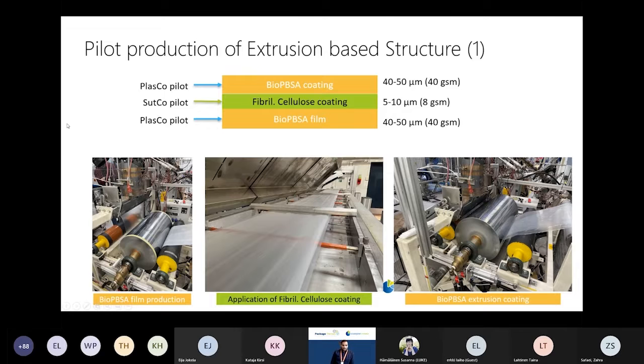So for production of structure 1, which was extrusion based, as we saw on the first slide, we had a bio-PBSA film produced on the Plasco line first, and then it was sent to our VTT SUTCO pilot line in Espoo, where we applied this fibrillated cellulose coating on top of this bio-PBSA film. Then it was sent back to the Tampere pilot line, and we applied another layer of bio-PBSA on top of that structure. In this structure, we had around 40 GSM of bio-PBSA on both sides, and the fibrillated cellulose coating was around 8 GSM. So this was the full structure produced on pilot.